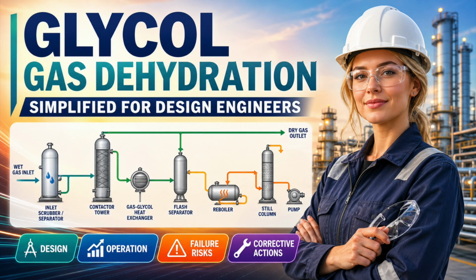Corrosion must also be examined by environment, not by generic material selection. Wet inlet gas, rich glycol, lean glycol, reboiler liquid, and still overheads are not the same service. Carbon dioxide, hydrogen sulfide, oxygen, water, salts, acidity, temperature, and deposits all change corrosion behavior. Rich glycol can become aggressive when acidity rises, oxygen enters, or degradation products accumulate. Still overheads can be highly corrosive where acidic vapors condense. Hydrogen sulfide introduces the additional risk of sulfide stress cracking.